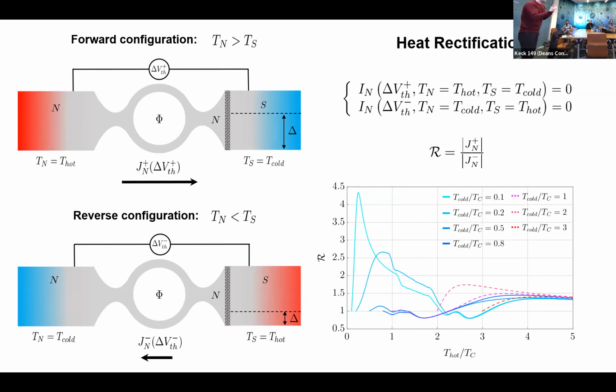To quantify this difference, this rectification, we can compute the so-called rectification factor, calligraphic R, which is simply the ratio between J_n plus and J_n minus. If it is equal to 1, you don't have rectification. If it's bigger than 1, you have J_n plus bigger than J_n minus, and so on. Here I plotted the result for this rectification factor as a function of the hot temperature and for different values of the cold temperature. What you can see is that, especially when T cold is very small, you get a rectification factor of the order of 4.5, meaning that the forward heat current is 350% larger than the reverse heat current. So it's for sure something sizable that you can measure in an experiment.